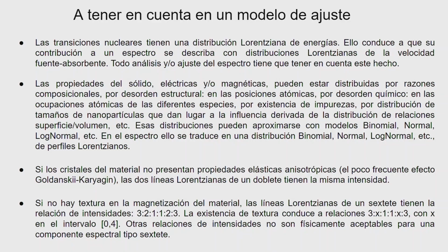And well, first of all, as Jean-Marc mentioned, in principle the transitions have Lorentzian shape. Then because of the way your sample was constructed, or the way your probes are distributed in the sample, the way the hyperfine interactions are distributed because of this or any other reason, the lines of your spectrum may not be Lorentzian. But you can always, in principle, unless you have dynamic effects, I mean, if you have a static spectrum, build your absorption lines as a sum of Lorentzian lines, with a physical criterion. You can do that. So remember that because this is important.